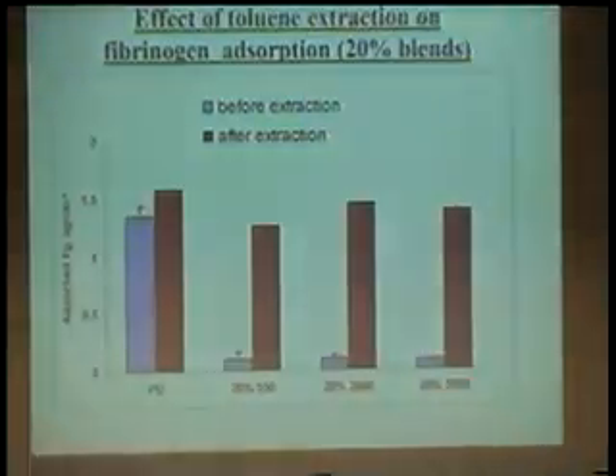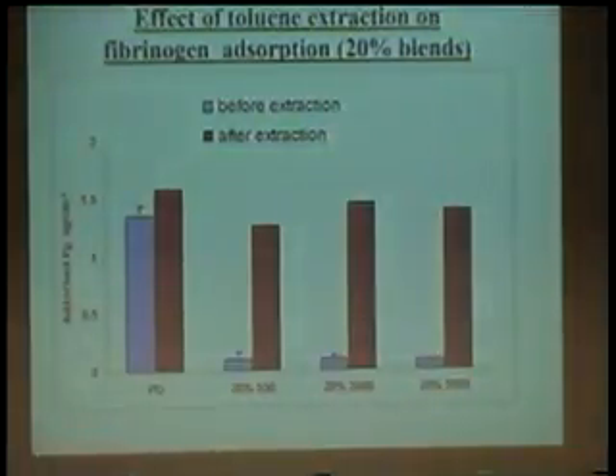So that's what it looks like. Now, if you look at the effect of toluene extraction on fibrinogen adsorption, that's shown here. It's the same materials I showed in the last slide. If you measure fibrinogen adsorption on the matrix material with no PEO, you find that it doesn't make any difference. You get the same high fibrinogen adsorption whether it's extracted or not.